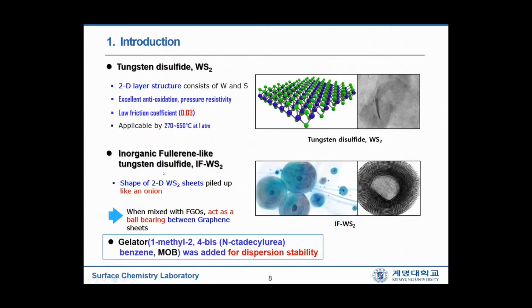IF-WS2 has a shape of 2D WS2 sheets piled up like an onion. When this is mixed with functionalized graphene oxides, it acts as a ball bearing between graphene sheets. Gelator, MOB, was also added for dispersion stability.